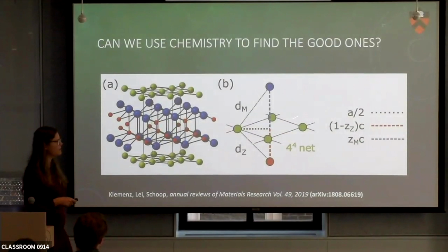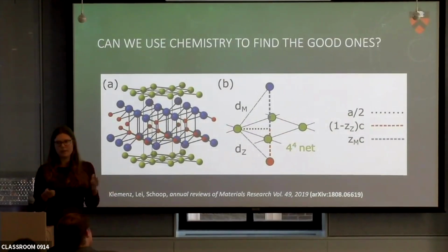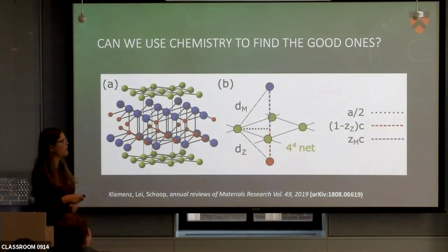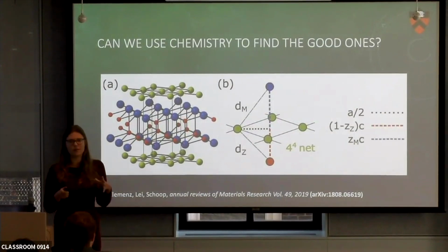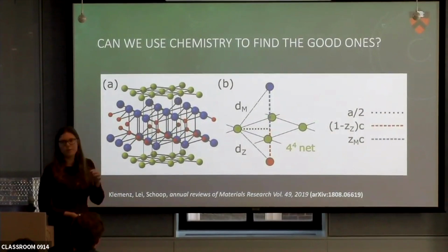Basically our hypothesis was, if the chemical delocalized bond is what is driving this whole band structure, or is one part of driving the band structure to be real, we want to have a shorter bond distance between the atoms in the net than to the next layer above or below, because then we can say they're bonded to each other in a chemical way within the square net, otherwise bonds would probably also form in the other direction.